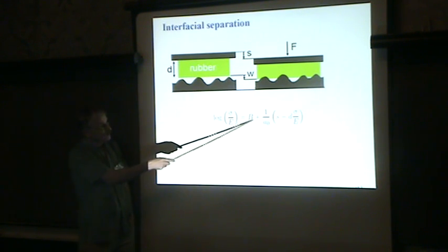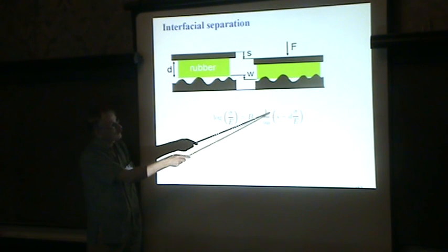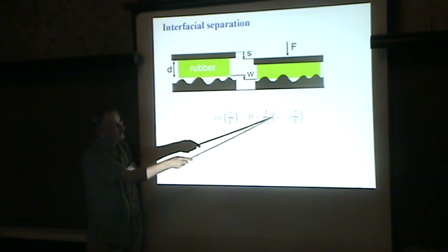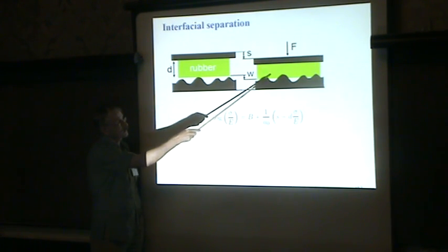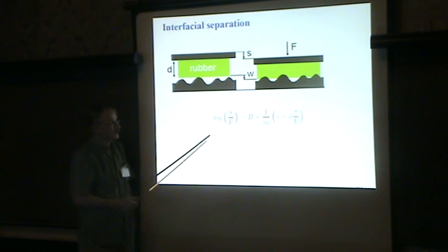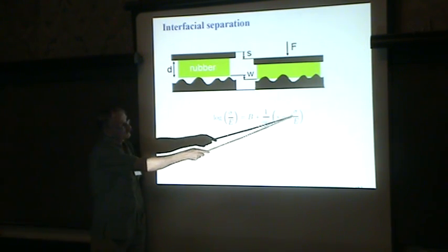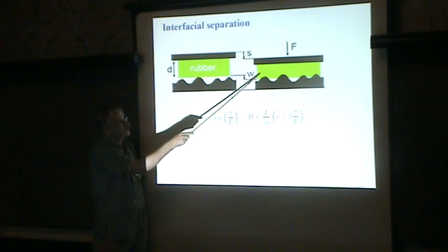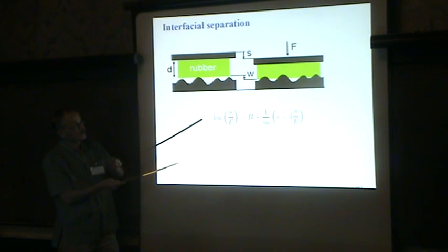You get the equation which looks like this. The logarithm of the applied pressure is basically linearly related to this penetration, which is given by the movement of the upper surface minus the compression of the rubber block, which is this last term. This simple formula for the compression is only valid if you have lubricated surfaces here, so the block can slip relative to the surfaces.